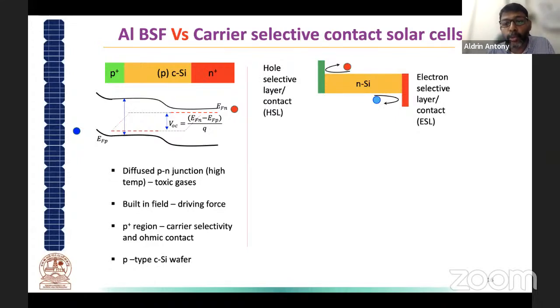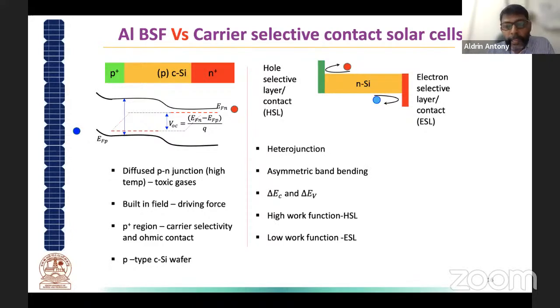on both the sides due to an asymmetry, and it gives band offsets. So it works with the right band offsets for electrons here and a band offset for holes on this side. And that we call a hole transport layer or electron transport layer for a crystalline silicon solar cell. And so this is a heterojunction concept. And there is an asymmetry in the band bending because of these band offsets. And then there are the band offsets, the delta EC for the conduction band offset, and the delta EV that we can call the valence band offset. So this is delta EV and this is delta EC. And there are high work functions.